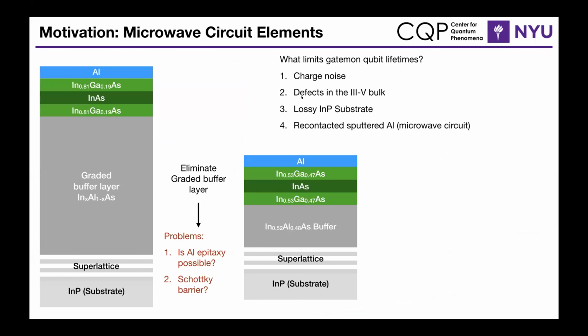So to combat these limitations, the first thing we do is address directly the defects in the III-V bulk. What we do is we eliminate the graded buffer layer, as seen going from this taller structure on the left to this middle structure. In this middle structure, you have just a constant composition of InGaAs, and you're straining the indium arsenide and the aluminum layers to that underlying InGaAs, which is lattice matched to indium phosphide. But this has a couple problems associated with it. One is, can you actually grow an epitaxial aluminum layer on this type of structure? And another one is you're actually increasing the Schottky barrier height. As you add gallium to this top InGaAs layer, you increase the Schottky barrier height at the surface, and that actually makes it harder to get the conduction band to dip below the Fermi level and get electrons in this indium arsenide channel.